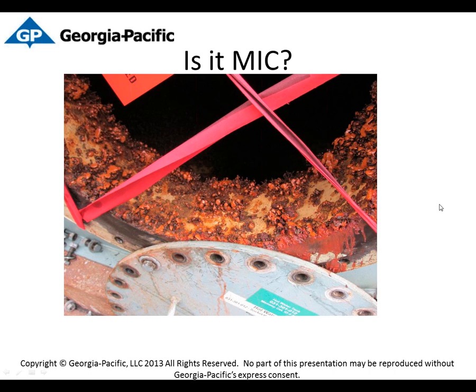This was another symptom we saw. This was actually something that the mill had known about, going on for a while. This is a hot water tank that feeds that hot water line. And about 8 years ago, I believe, the decision was made to build a carbon steel tank, and the plan was to just run it to failure because it had the same failure mode beforehand. So we've got a 250,000 gallon tank here that we knew we built, and we knew it would probably only last 10 years due to these tubercles, but no one really knew what they were. Like I said, we thought it was a manganese problem because that's what the history of the mill's water treatment was.